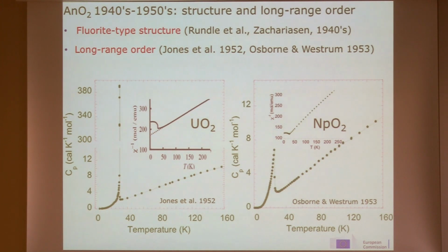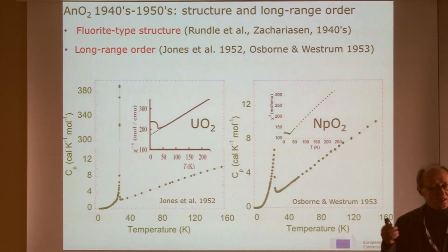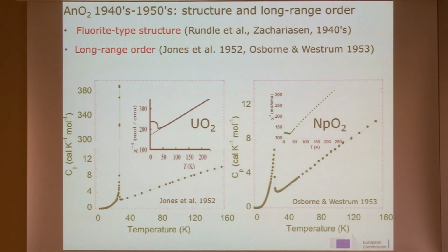But on the other hand, the muon spin relaxation experiment showed an oscillation in the signal, in the forward-backward asymmetry signal, indicating that a magnetic field was present at the site where the muon was implanted. So time reversal symmetry was broken. Neptunium dioxide was the first example of what was called hidden order, in a system showing a similar puzzle later on, URu2Si2.